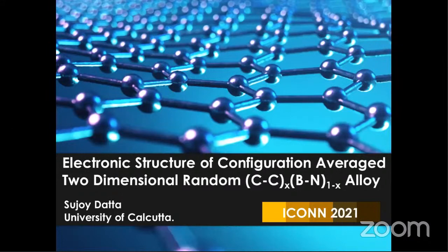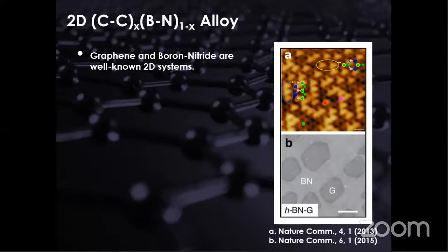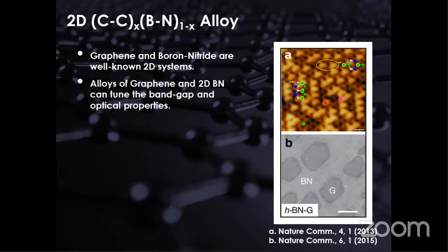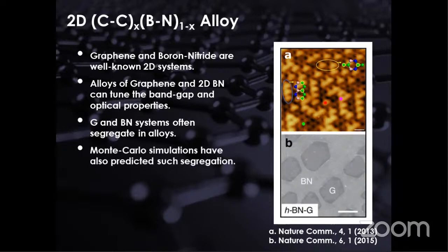Okay, thank you. Good afternoon, everyone. The title of my talk is Electronic Structure of Configuration Average Two-Dimensional Random Graphene Boron Nitride Alloy. As we all know, graphene and boron nitride are very well known today. Graphene is a zero band gap system, and boron nitride has a wide band gap. So from the very beginning, people tried to make alloys of them to tune the band gap. But experimentally, it is found that in many cases, graphene and boron nitride start to segregate. Even in theoretical Monte Carlo simulations, similar results have been found.